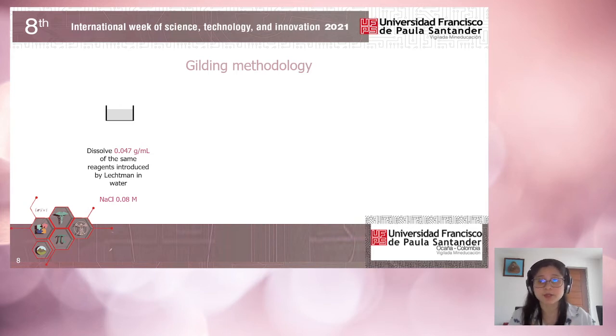Because Heather Lechtman used a 1:1 ratio, this molarity was transformed into mass using the molecular weight of sodium chloride because it was the lightest one among the three salts that Heather Lechtman used. This gave a concentration of 0.047 grams per milliliter.